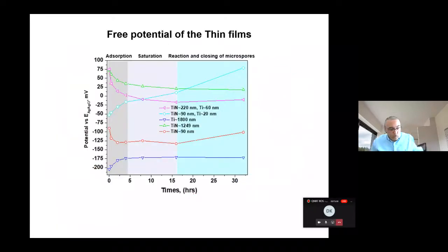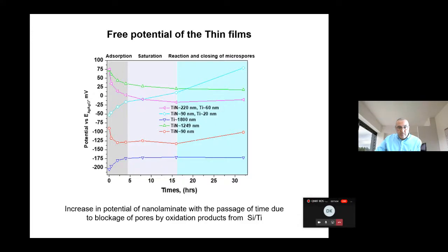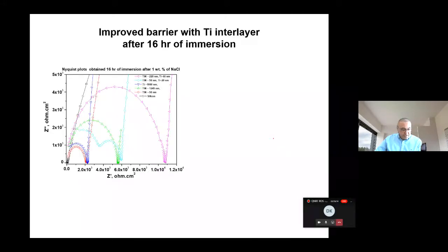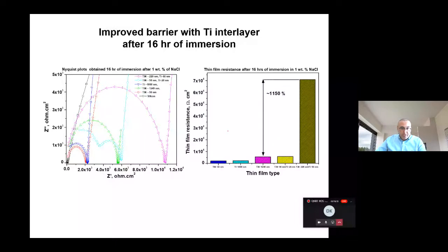Now, in year 3, we wanted to look at some of the corrosion response of these materials, and as you can see, if you look at the different combinations, you would notice that the behavior for the titanium nitride with the inner layer tends to be far superior, and we had a hunch that it had to do with how much blockage the thin titanium layer was offering, or the thick titanium inner layer was offering. So we went ahead and did some electrochemistry studies on these materials, and again you would notice that initially we could see that the response for the inner layer that was thick was superior by 1,000% when it comes to corrosion protection, and these are about 16 hours.